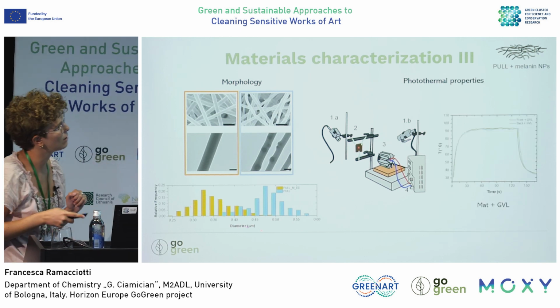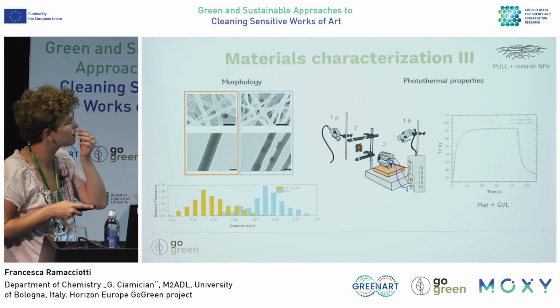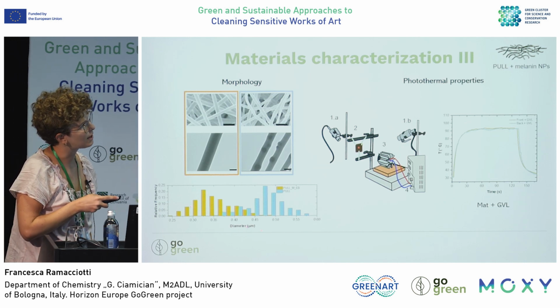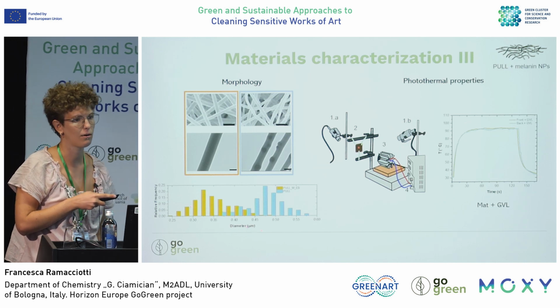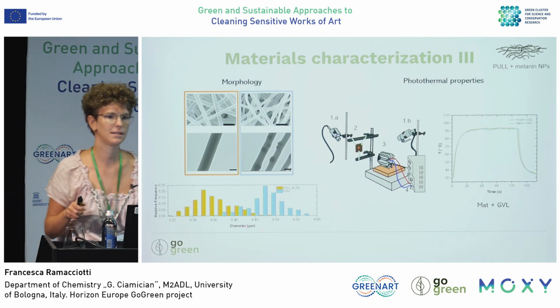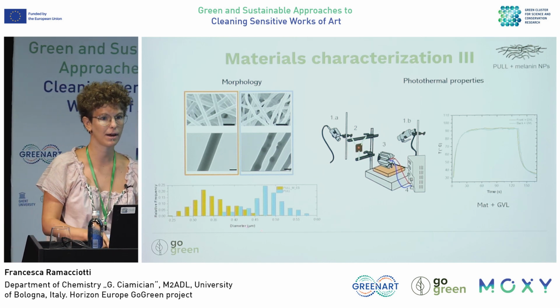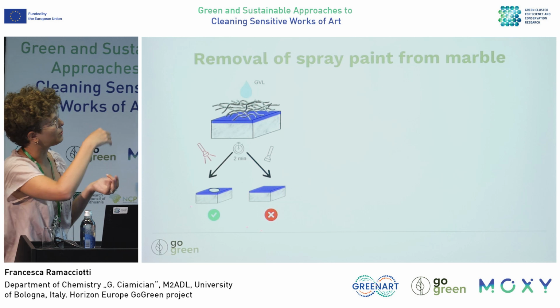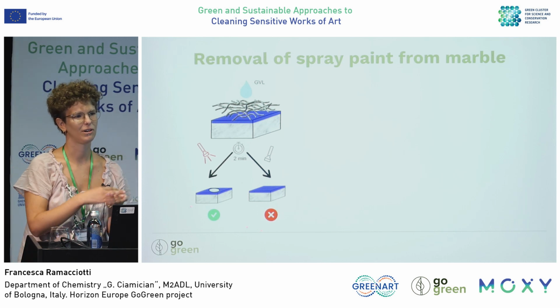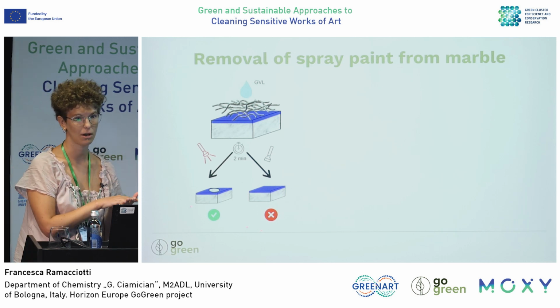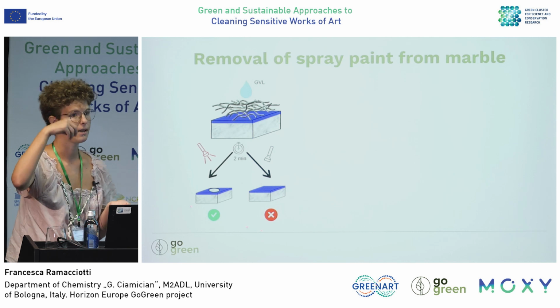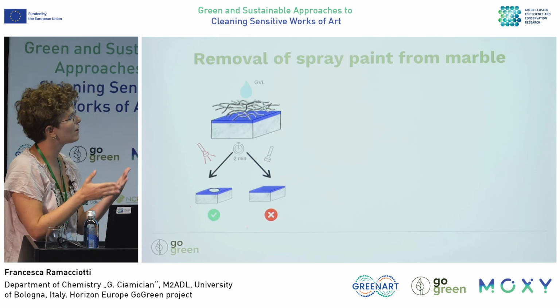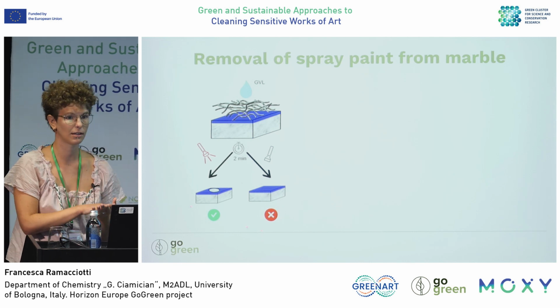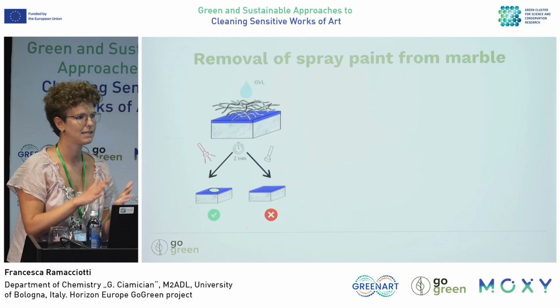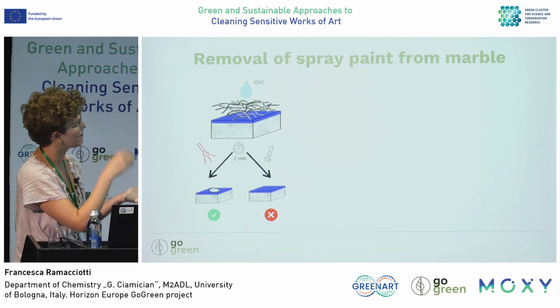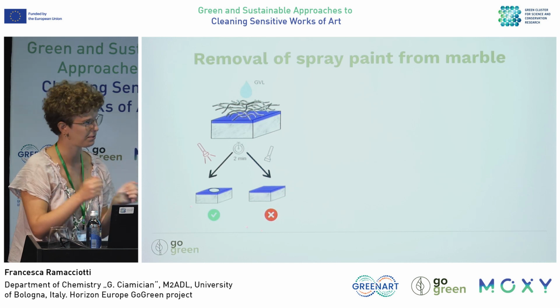When you add the solvent, in this case gamma valerolactone, the maximum temperatures of the back and the front are almost the same. So this means that when you are applying your mat on a tissue and you are irradiating, you cannot monitor directly the temperature in contact with the object, but you can only monitor the temperature on the surface. So what you know is that the temperature in contact with the object is at least the same as the one that you are monitoring on top.